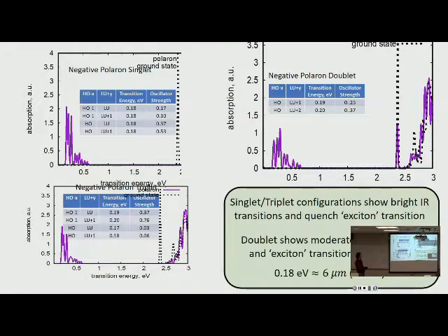In the singlet and triplet, you don't see exciton photoluminescent oscillator strengths; that gets quenched. But in the doublet, you still see potential for the across the band gap emission. That indicates that if you want to completely quench visible light excitation, you have to put in 2 charges, or take out 2 charges, to get the IR emission, because for the doublet you just put in 1 or take 1 charge out. So the optical spectra gives a potentially positive result that efficient IR emission might be possible in the regions that we want.